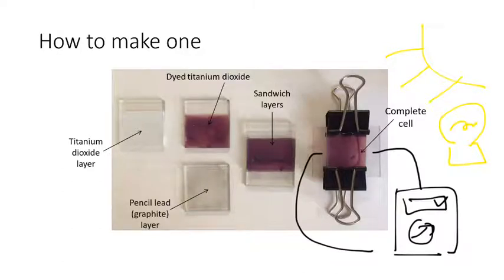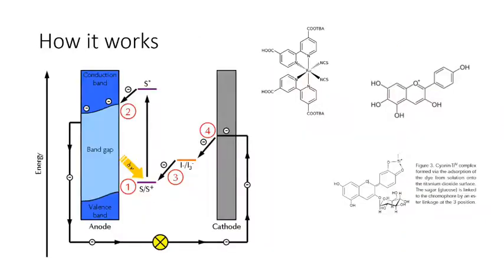There's my light bulb. And so how does this work? If we think about the valence band and the conduction band of the TiO2. Okay, so here's our TiO2. The sensitizing dye is represented by this S. So when light excites the dye, an electron moves from the ground state to the excited state. We see that the energy of the excited state is above the energy of the conduction band of the TiO2. So that electron gets transferred to the conduction band, where it can then connect with the electrode and flow